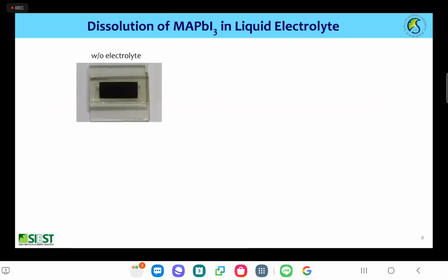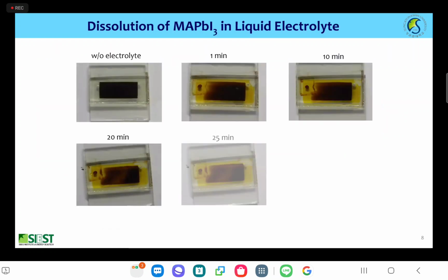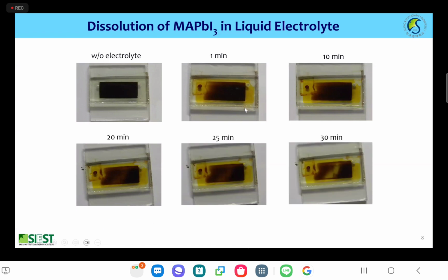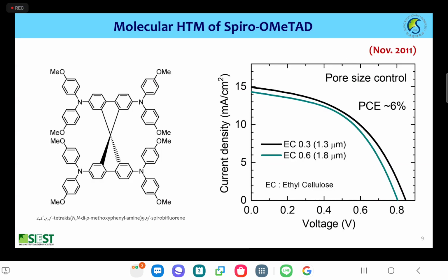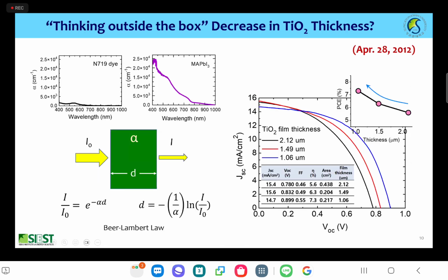But as I mentioned, there is a dissolution problem of the methylammonium lead halide perovskite in the presence of liquid electrolyte. Then we had to switch this liquid electrolyte to a solid hole-conducting material. We introduced the spiro compound into the mesoporous titanium oxide, and we achieved 6% efficiency on the first trial. However, when we increased the film thickness, the efficiency did not improve.